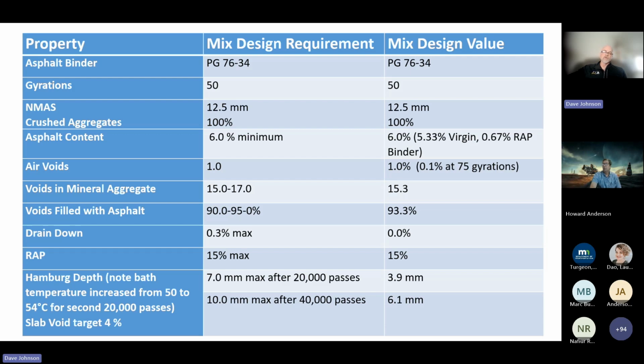And then you can see the Hamburg results for this mix after 20,000 passes. And there was an adjustment made. We talked about in the initial work how they had added weight to the Hamburg. Now, instead of adding weight, they changed the temperature, bumping it up 4 degrees centigrade.